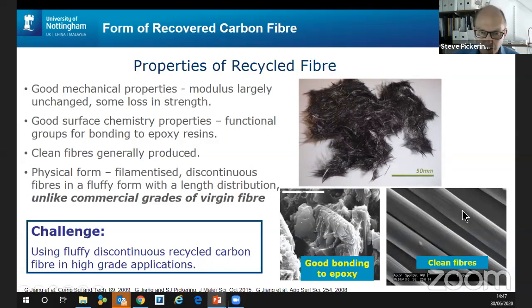And you can produce good clean fibers, as I've shown here, but it's in a fluffy form. There's quite good surface chemistry. Quite a lot of publications have shown that there are good functional groups still left on the surface of these fibers that provide good bonding to epoxy resins. So you don't necessarily need to resize the fibers. The sizing that was originally on the fibers has been degraded along with the polymer, but nevertheless, you don't necessarily need to resize them, because they will bond well to epoxy resins, as shown just here.